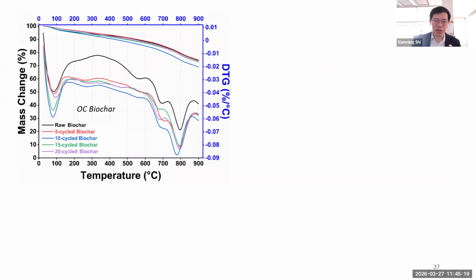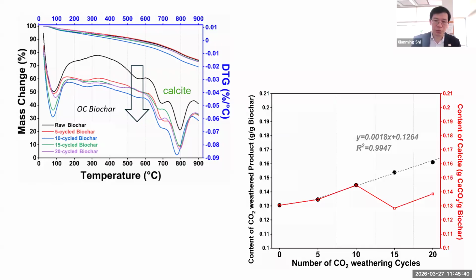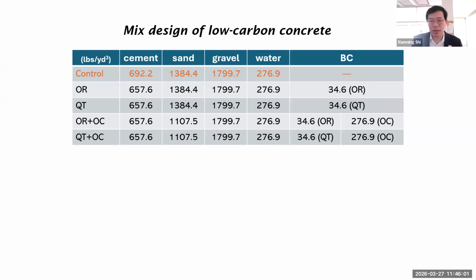Again, we did the TGA, or thermogravimetric analysis, which shows that there is a peak between 500 and 600 degrees. As we subject biochar to more cycles, that peak sort of disappeared. However, here's another peak, which corresponds to calcite. It increases over time. When we plot it, the x-axis is the number of CO2 weathering cycles. The y-axis on the left is the amount of CO2 weathered products. The black line is almost a linear increase over the number of cycles. However, if we only focus on the calcite as part of the product, it sort of peaked around 10 cycles, which is the red line.